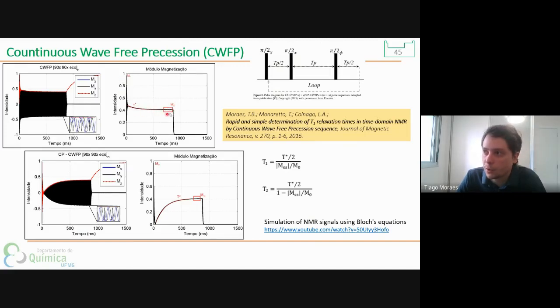And from the signal, we can extract three values. That is the M0, the initial amplitude, a time decay of the signal here that we call T star, and an amplitude in the steady state, that is the MSS. And from these three parameters, we can calculate the T1 value and T2 value simultaneously. So with just one experiment, you can determine the mean value of T1 and T2 very fast. So it's a very fast pulse sequence. For example, for industry, if you want to monitor some very fast process like flux and so on.